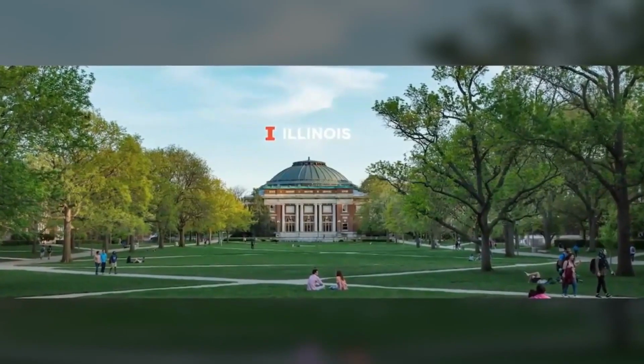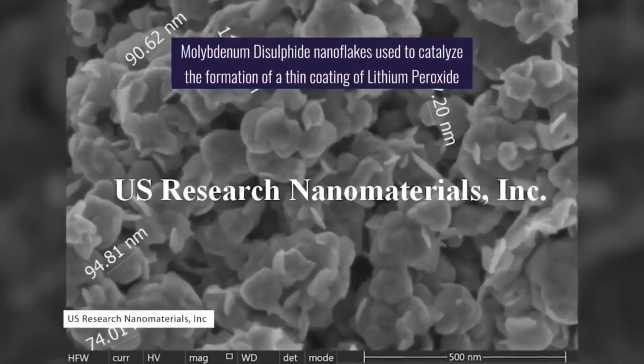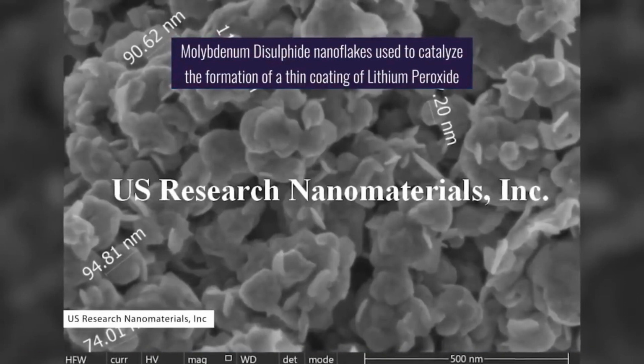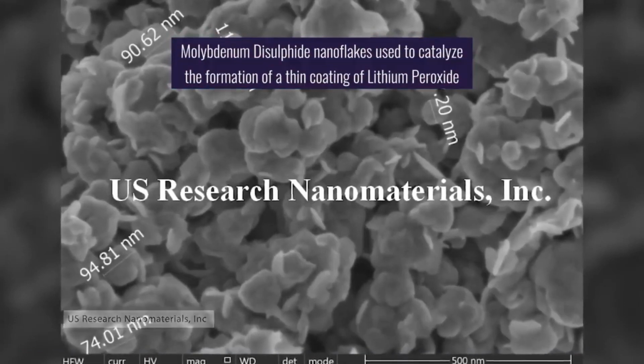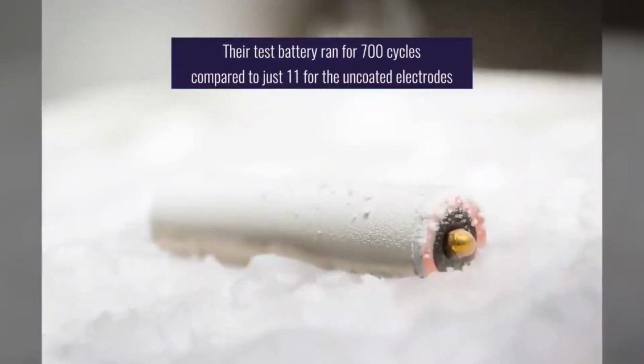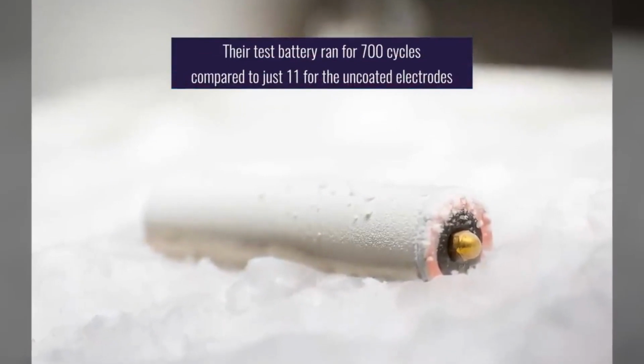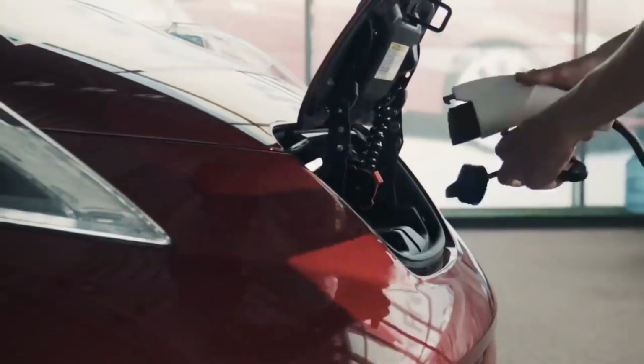Researchers at the University of Illinois found that they could prevent this clogging by using molybdenum disulfide nanoflakes to catalyze the formation of a thin coating of lithium peroxide on the electrodes. Their test battery ran for 700 cycles, compared to just 11 cycles of an equivalent with an uncoated electrode. While this isn't enough lifetime for a car, it's a promising hint of things to come.